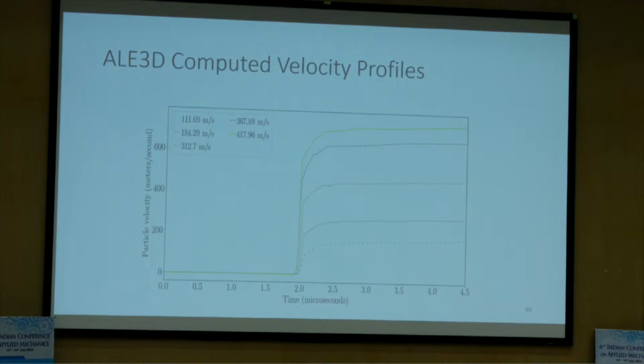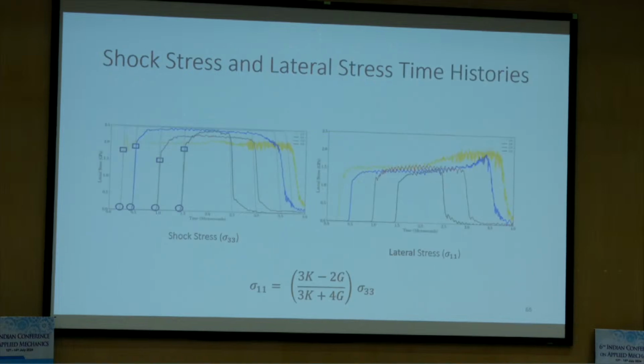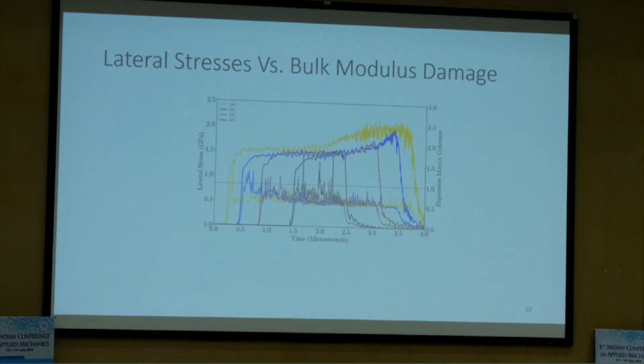And this is the simulation of the plate impact test of different velocity. You can see that very nicely. See that this is the lowest velocity, that's the highest velocity, and Hugoniot elastic limit, and you see the dispersion of the wave, and it reaches the peak that is controlled by equation of state. And also we did some diagnostics to see lateral stress versus bulk modulus. That's damage. The lateral stress is constant and then it increases. This axis is bulk damage. Below 1 means no damage, above 1 damage. You see that it's all below 1. So the bulk modulus is not changing much.